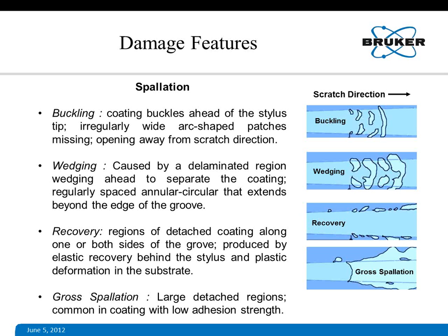Coating buckles ahead of the stylus tip, with irregularly wide arcs and patches missing on the coating surface, and they open away from the scratch direction. Wedging is similar to that, but here these are more pronounced patched areas where coating is actually removed by wedging. They are annular structures and they open away from the scratch direction.